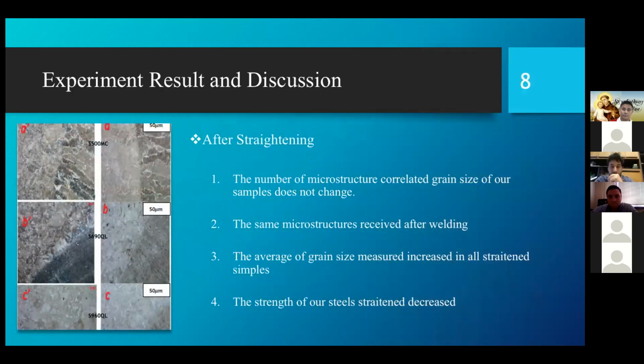So as we checked the microstructure after the straightening of all our materials, the main microstructure received after welding persists, and the number of microstructures and the grain size correlation does not change as well. The average grain size measured increased in our samples, which can affect the strength of our straightened steel. That means the strength of the material after the straightening decreased.